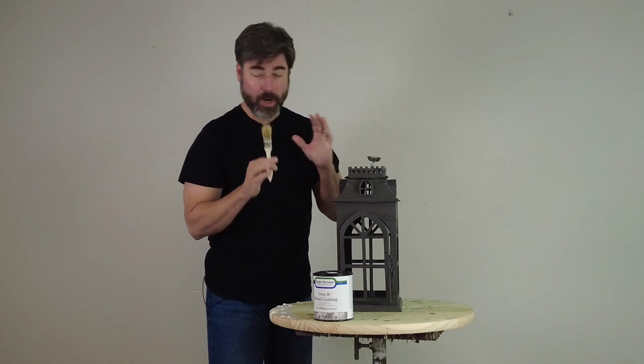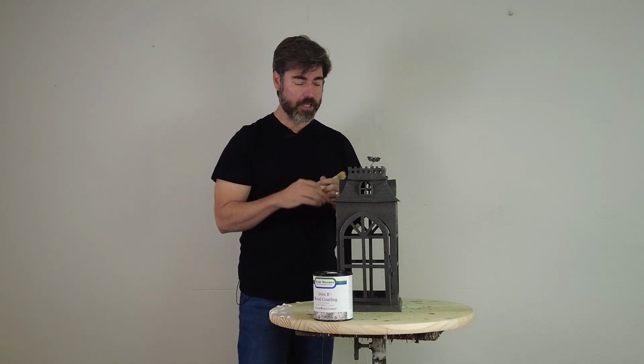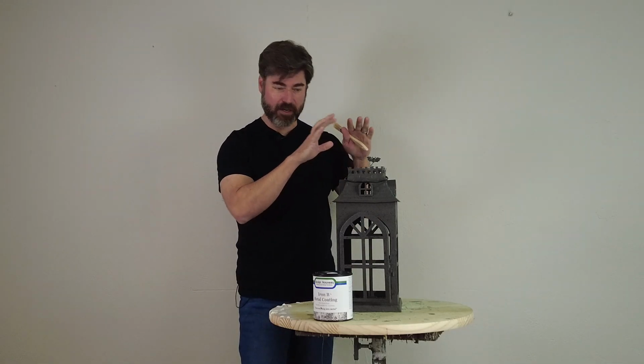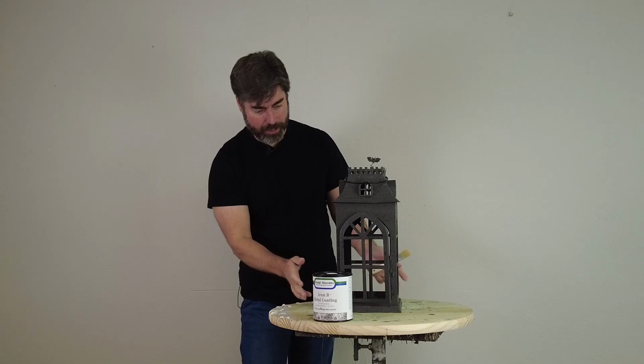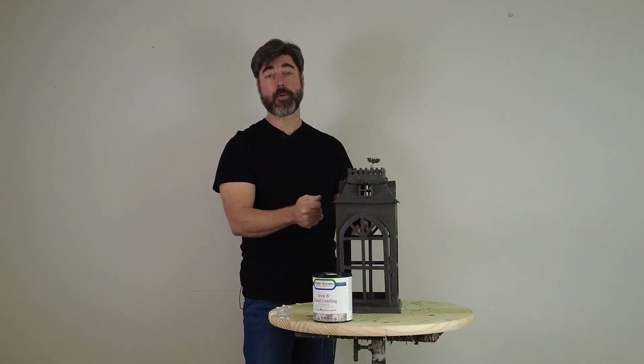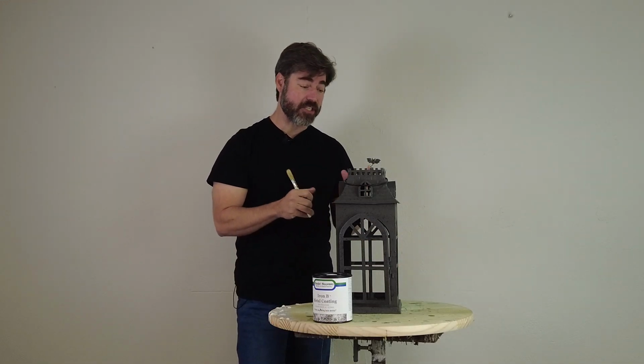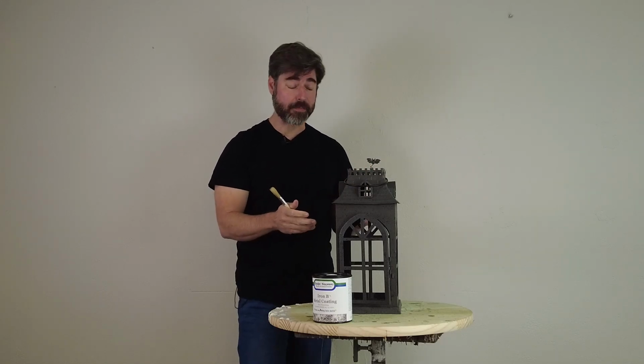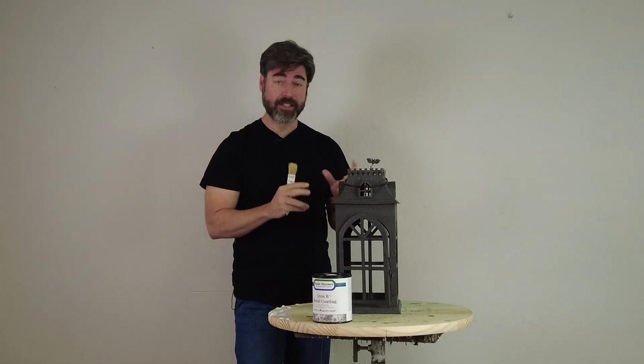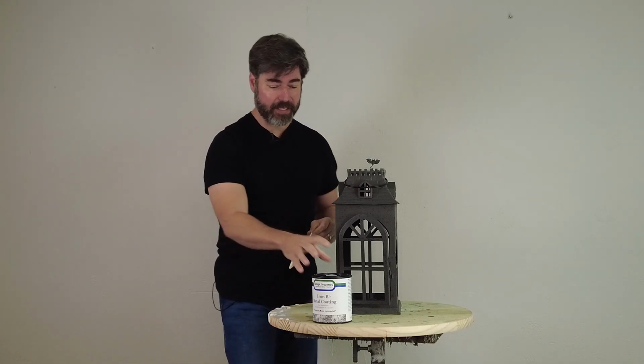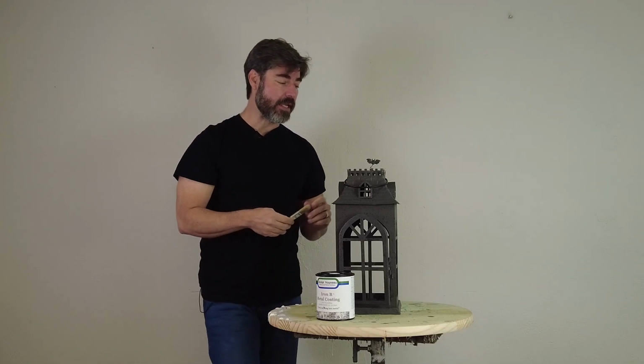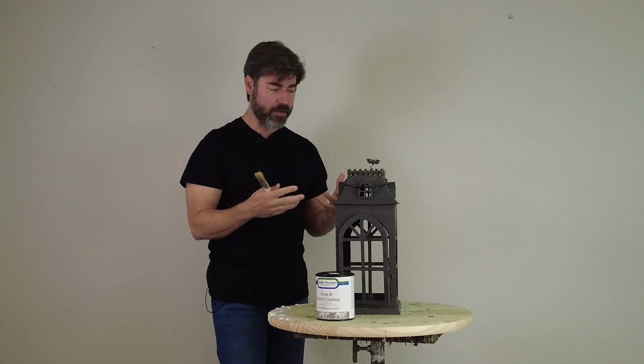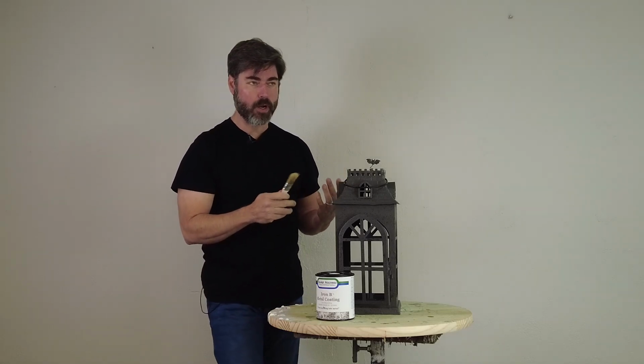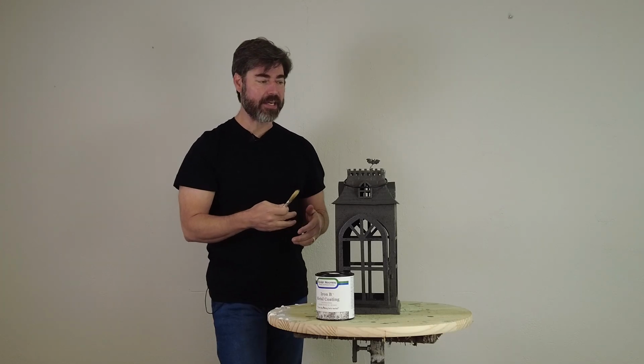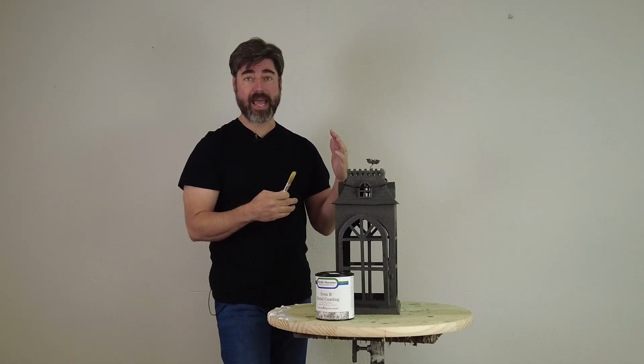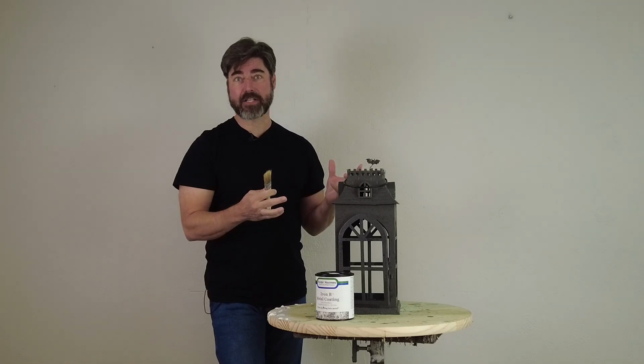So again, with this coat, it's really important that we apply our metal coating to everything we want it on and be ready immediately with the patina. Because if you wait too long to apply the patina, then you're going to get little to no reaction. And another thing about that reaction with your Iron B is to get a good oxide forming, we really want mild temperature and high humidity. The higher humidity we have, the better reaction we're going to have.